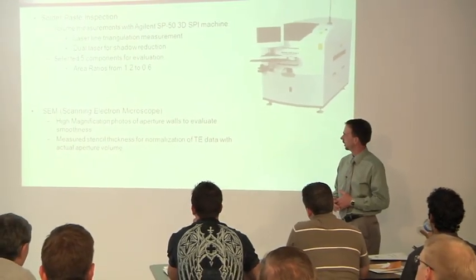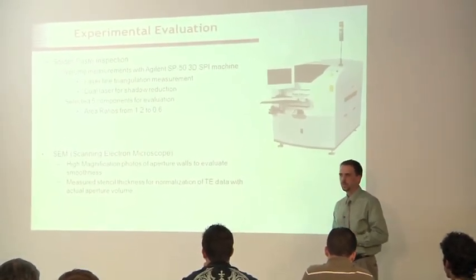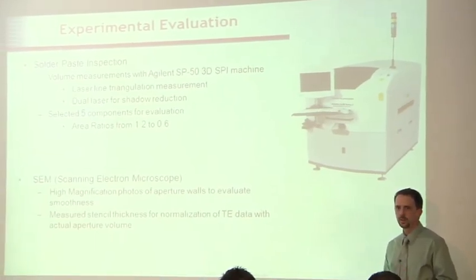So, just a little bit about how we went about evaluating this. Joel talked earlier about the OMRON solder paste inspection. We have a solder paste inspection in our facility. This is a picture of it. It's the same type of method as what Joel was talking about, I won't go into that, but we looked at, on this particular board, area ratios from about 1.2, which is a nice big beefy pad that we should be able to print all day, all the way down to an area ratio of 0.6, which violates that 0.66 threshold that's kind of been the standard. And then we also, we have a scanning electron microscope in our Mayfield Heights facility. We use that to get some nice pictures of the surface of the walls, as well as measure the stencil thickness to kind of do some normalization of the data.